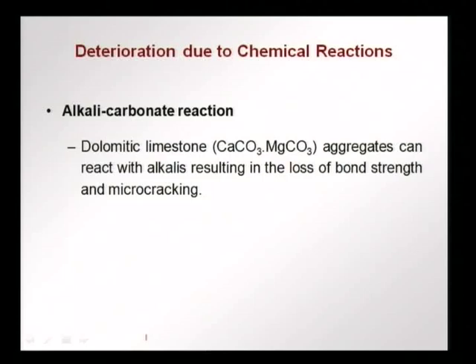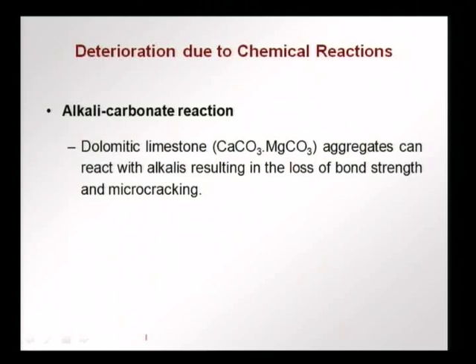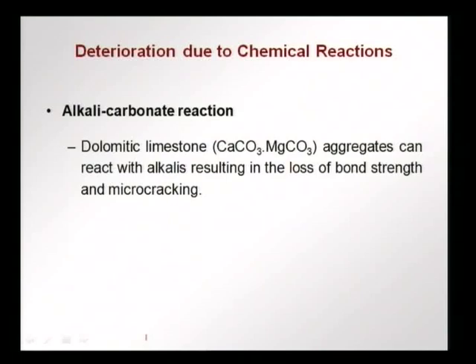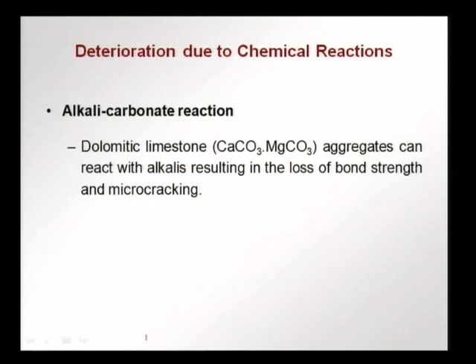Just as we have alkali-silica reactivity, we can also have alkali-carbonate reactivity, where carbonate-based aggregates react with the alkalies. This happens with dolomitic limestone, where calcium carbonate and magnesium carbonate are both present and can react with the alkalies, resulting in loss of bond strength and microcracking. We must be careful when choosing aggregates to ensure they do not contain reactive silica or reactive carbonates that could cause durability issues.